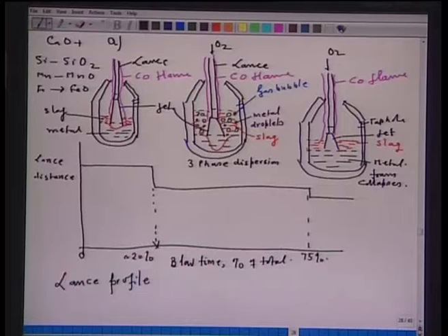as a result silicon gets oxidized to SiO2, manganese to MnO, and iron to FeO. Now, as I have said, in some practice calcium oxide is also added in order to form a slag for removal of phosphorus. So, in the initial period of blow, it consists of oxidation of impurities as well as iron, and the beginning of slag formation, which starts with the dissolution of calcium oxide, because unless calcium oxide dissolves and a basic limey slag forms, there is no chance for removal of phosphorus in the later periods of the blow.